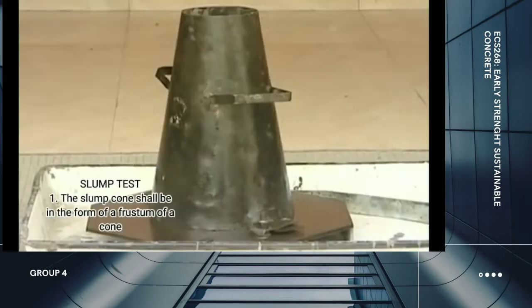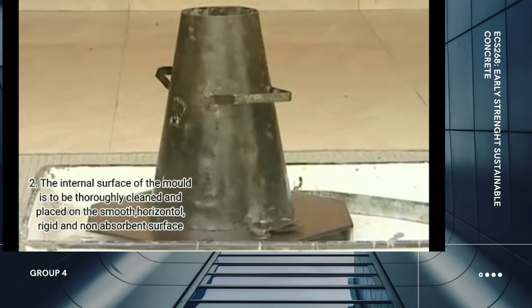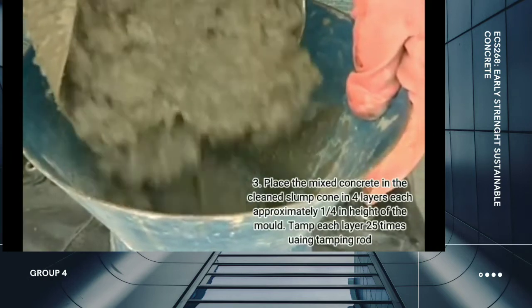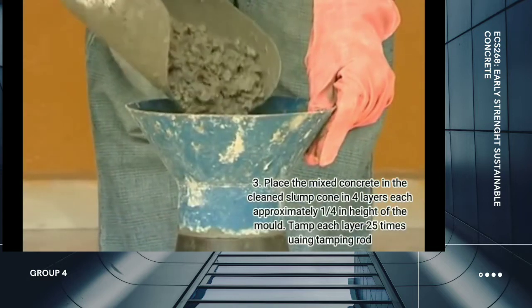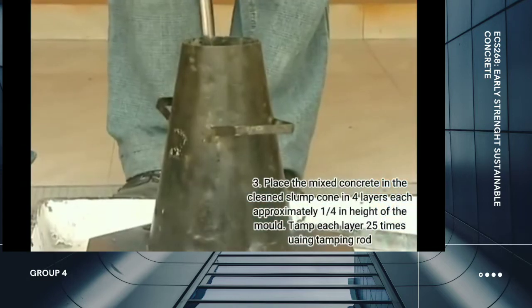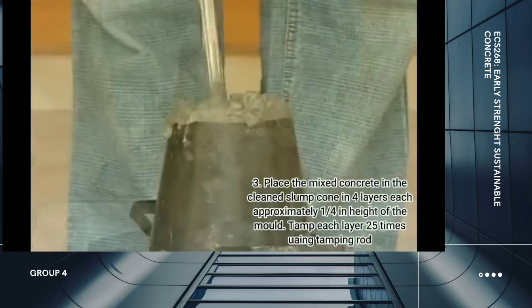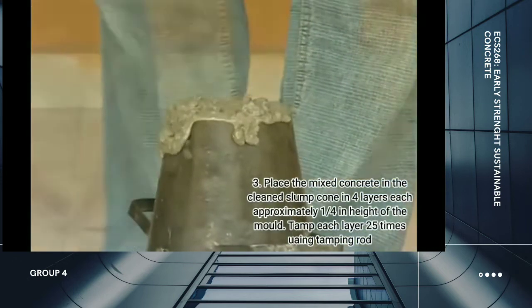Next, we will conduct the slump test. The slump cone shall be in the form of a frustum of a cone. The internal surface of the mold is to be thoroughly cleaned and placed on a smooth, horizontal, rigid, and non-absorbent surface. Place the mixed concrete in the clean slump cone in 4 layers, each approximately 1/4 of the height of the mold. Tamp each layer 25 times using a tamping rod.